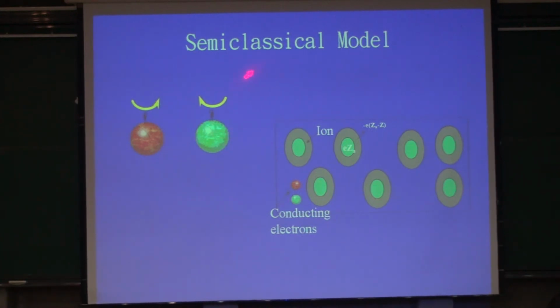But I think in the semi-classical way, with the Drude model, if you consider why those things were only observed after 1988, there are several reasons. One is that if you use the Drude model to explain this, because the electron has charge and spin, you can consider it in a semi-classical way, the up spin with this and down spin with this, counterclockwise and clockwise. And if you have two electrons, they both carry the charge, but they have different spin. So when they transport in the material, they are scattered in different ways. Some kind of scattering will be within the mean free path range. They have some possibility for scattering.